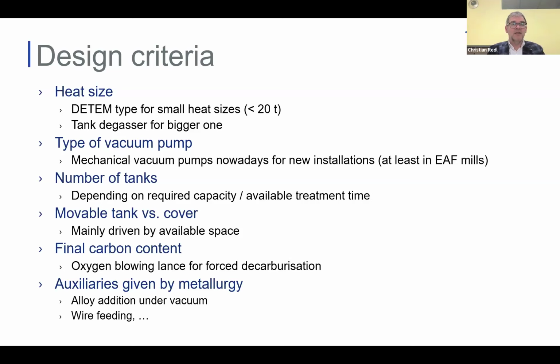The final carbon content and also the product mix dictate if you need oxygen blowing lance for forced decarburization, or you only go for a simple vacuum treatment. And the auxiliaries which you're installing on your vacuum plant, like a wire feeder or alloy addition system under vacuum, are mainly given by the product mix which you have in mind.